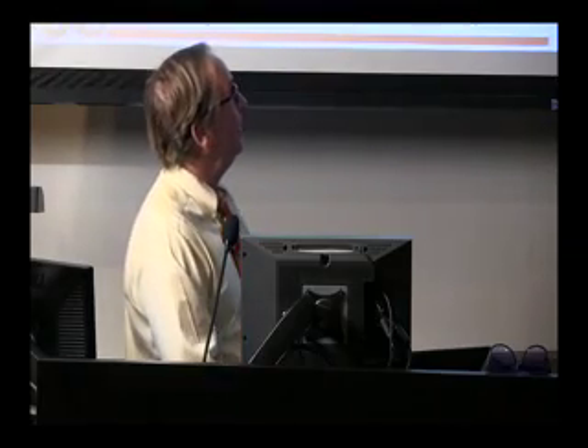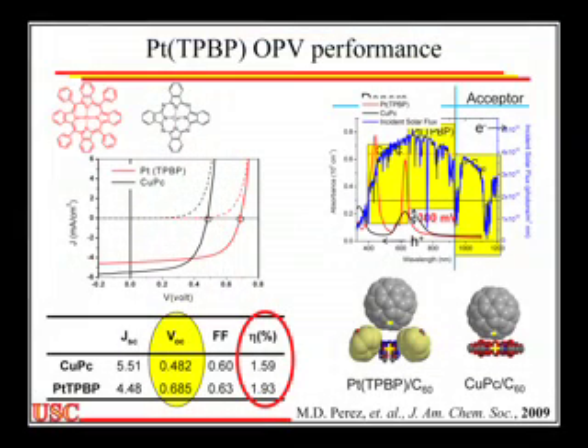The reason is if you look at the energetics of these, the energy of the hole, approximated by the HOMO energy, is less for the platinum porphyrin than for copper PC. The energy of the electron is fixed by the reduction, the LUMO level of C60. And so this energy difference between the hole and the electron should be related to the open circuit voltage, and it doesn't appear to be. In fact, it's inversely correlated. A small interface energy difference gave rise to a fairly large open circuit voltage.